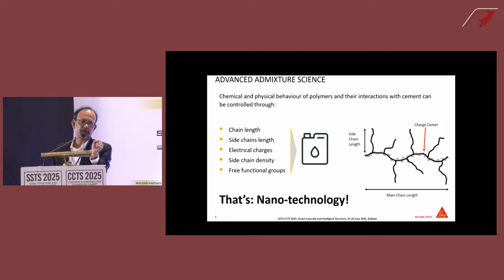But it's not only about dispersion. It is also about controlling the mix quality, the ease at which the concrete can be mixed, and less vibration. You can have a concrete where you vibrate for 15 seconds, then it will spread. Then you have another concrete, 5 seconds, it will spread very easily, no blowholes. When you remove the formwork, you look at fair face concrete. And then there is another concrete where you don't have to vibrate at all. Less labor, less energy. Vibration also requires energy; it requires some sort of fuel, and it requires people to vibrate.